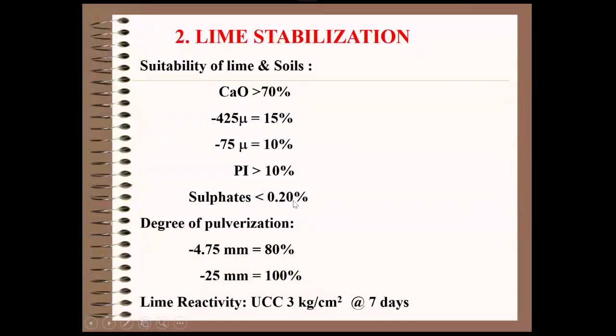And sulfates, if they are present in higher content in our soil, then also we should not go for lime stabilization, because lime plus sulfates produces another unwanted mineral called ettringite, which by itself is another swelling mineral. That ettringite unnecessarily damages the pavement system when it swells, like black cotton soil. So that is why, when we are going for lime or cement stabilization, these are some of the checks. There are certain failures also when these sensitive points are not followed, right?